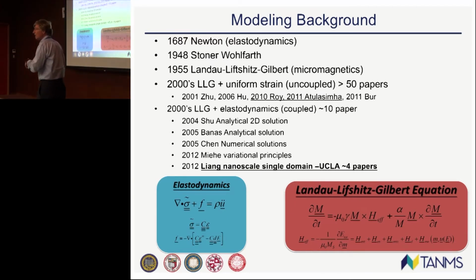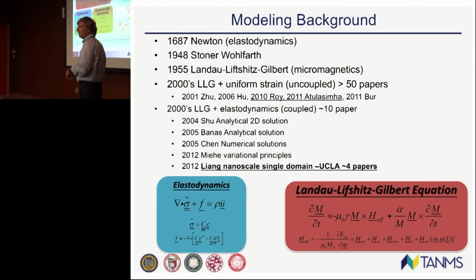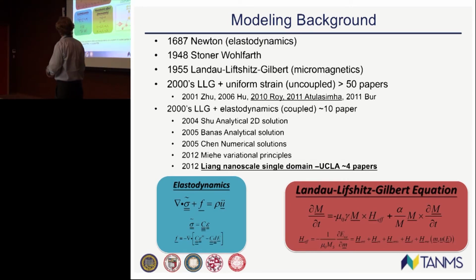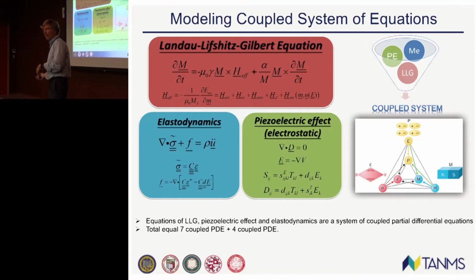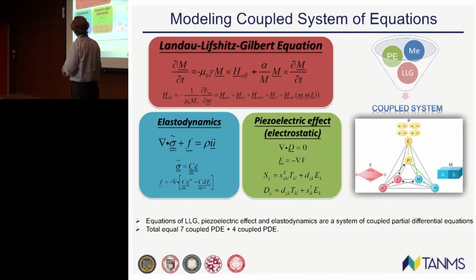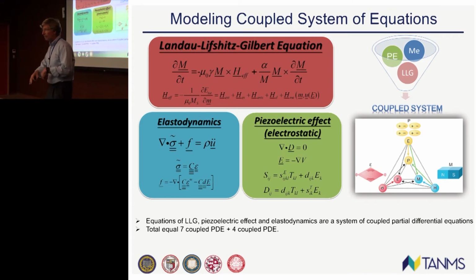Let's dive down into a little more detail, okay, guys? So if this is Landau-Lifshitz-Gilbert, and let's say you all work with Landau-Lifshitz-Gilbert, you look at the effective field term here, and you say, well, what's the effective field term divided up into? You have things like the external magnetic field, right? The exchange coupling term, the magnetocrystalline anisotropy, the demagnetization field, and let me pause here. This is where your ears should perk up: a magneto-elastic term. H effective, which is induced by magneto-elastic coupling, and that's where you get those changes in magnetic anisotropy. What's it a function of? See this term here, U, displacement. Where does U come from? Well, that comes from elastodynamics. That's Newton. Newton said, well, hey, I can actually tell you what the variation in U is for given stress or strain fields. So these equations now are coupled. They are not independent.